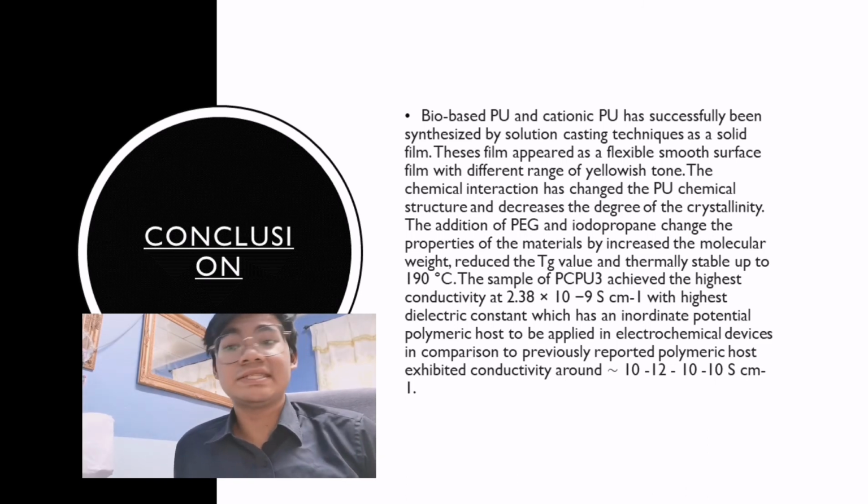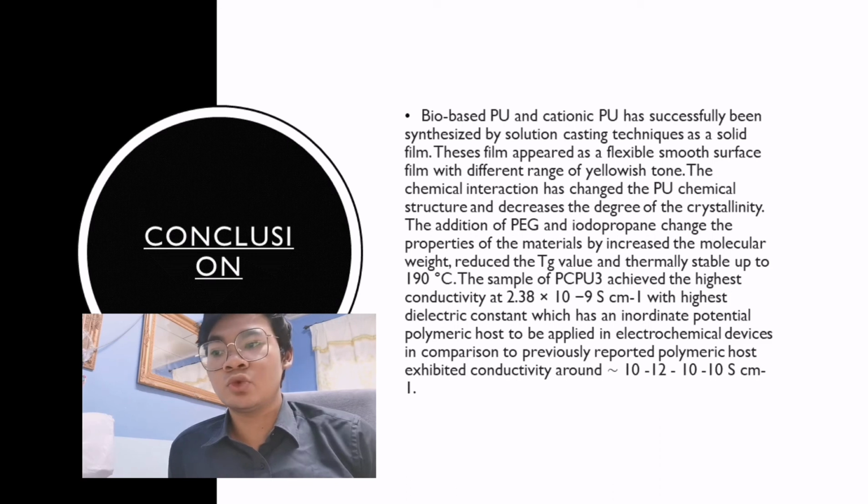The sample PCPU3 achieved the highest conductivity at 2.38 times 10 to the power of negative 9 S/cm with the highest dielectric constant, which has great potential as a polymeric host to be applied in electrochemical devices.